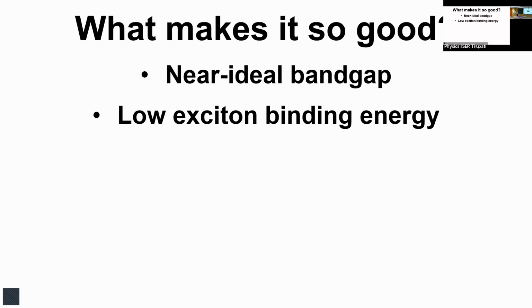Why is that important? Because if the two are bound very strongly, they will not become current, because you have to break them apart and take the electron in one direction and the hole in the opposite direction. So you want the excitonic binding energy to be low compared to thermal energy. If it is much larger, more than 100 milli electron volts, it's not going to be useful. So the exciton binding energy needs to be low. These materials have intrinsically low exciton binding energy.